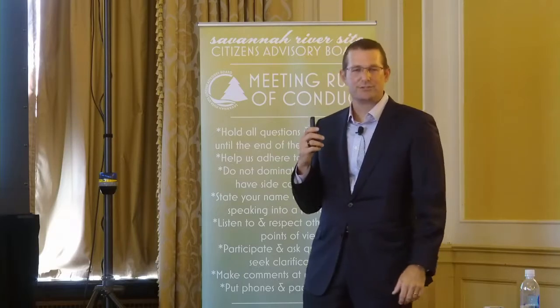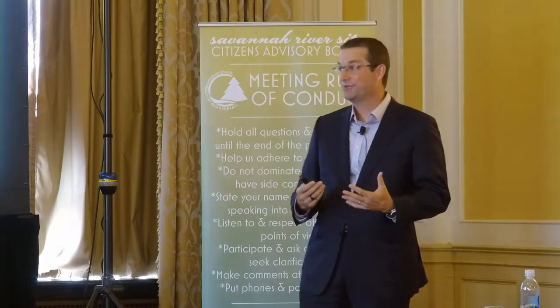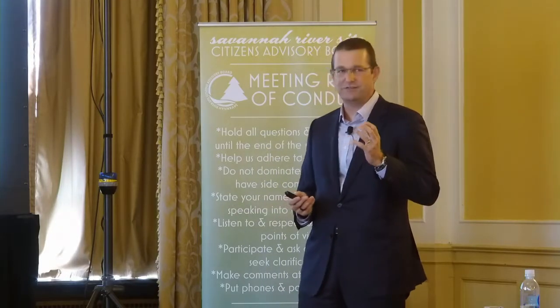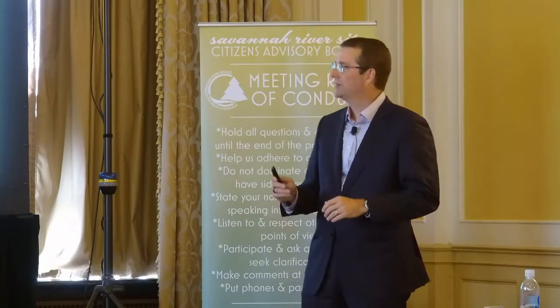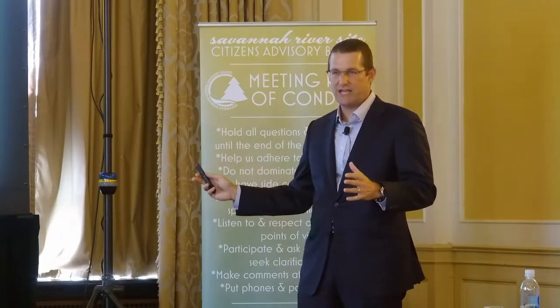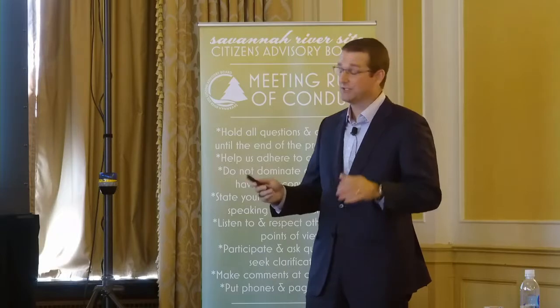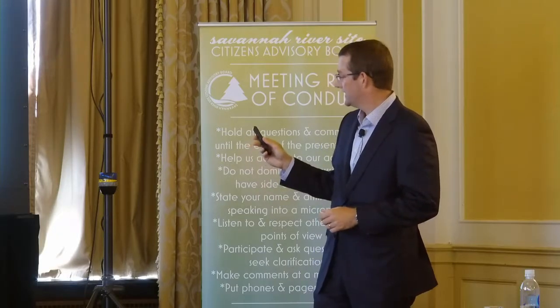I've had a lot of people describe fresh saltstone as being of the consistency of latex paint. It's actually much thinner than latex paint. You'd be astonished that it turns into the final product that it does, because it actually has a consistency very close to chocolate milk. So it's highly flowable. That's why we can use the very large disposal units we have and not worry about it not being self-leveling. So that's the mixer.